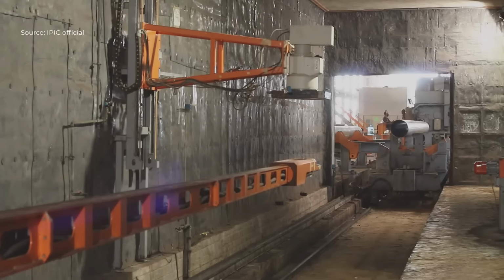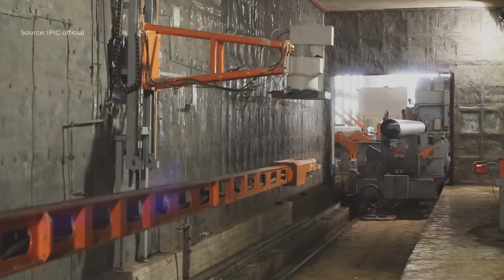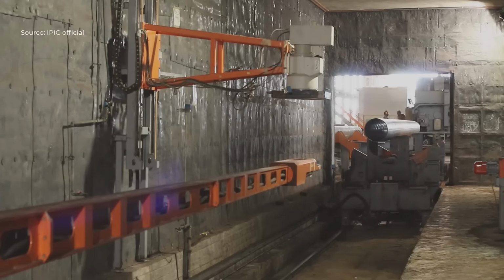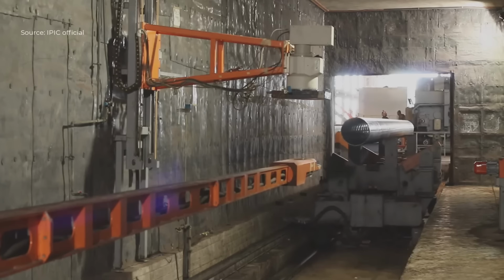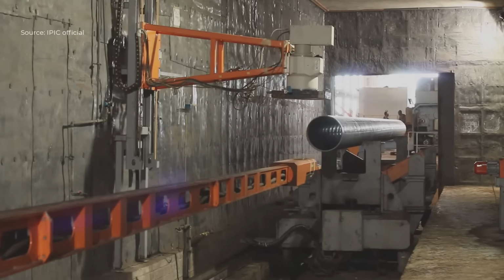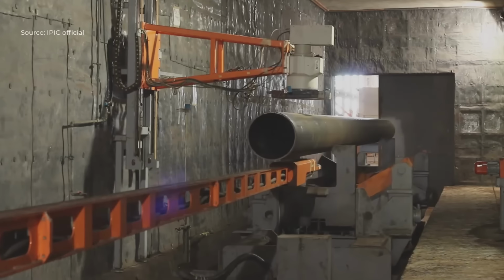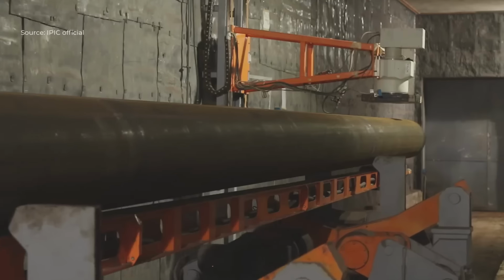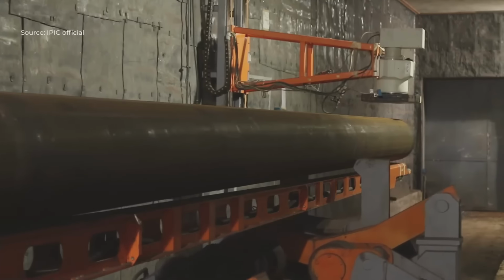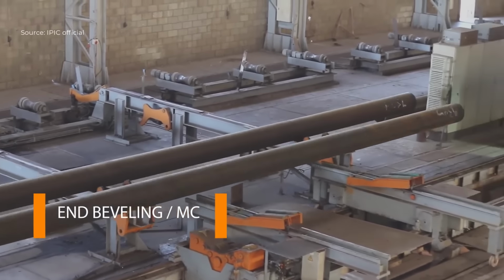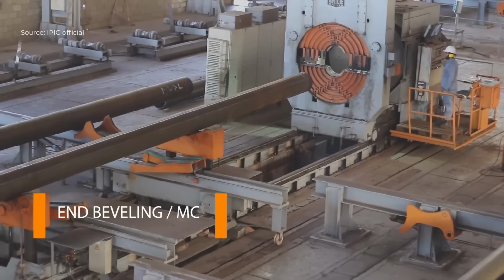Following hydrotesting, non-destructive testing begins. The ultrasonic testing machine is used for welding detection, scanning the weld seam for internal flaws, such as cracks, inclusions, or lack of fusion. Then, the pipe is inspected by an X-ray real-time machine, which provides continuous imaging of the weld to identify any internal defects not visible to ultrasonic testing.